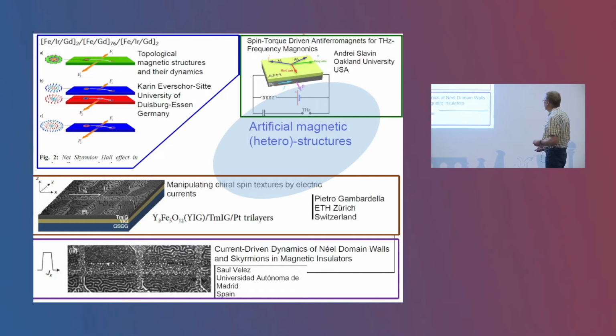That was very nicely overviewed, I think it was today or yesterday, maybe today, in this plenary talk by Pietro Gambardella on manipulation of chiral spin textures, and a related talk by Saul Velez on the current-driven dynamics of Néel domain walls. Well, also manipulation of the skyrmions in multilayers. This kind of magnetic multilayer was highlighted in the talk by Karin Everschor-Sitte today on how one can control, for instance, the skyrmion Hall effect, to enhance it, to suppress it, and to manipulate this kind of interesting transport phenomenon.